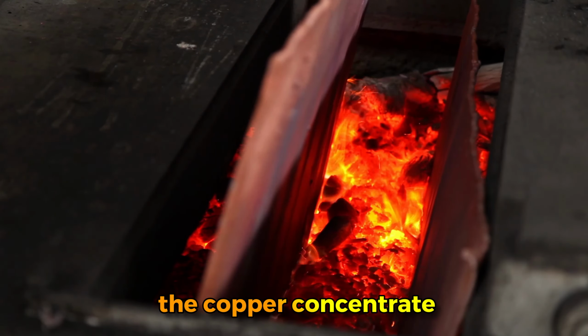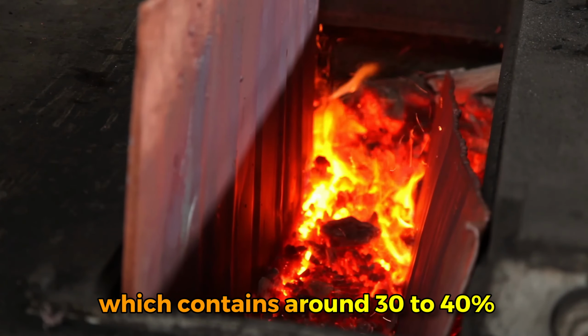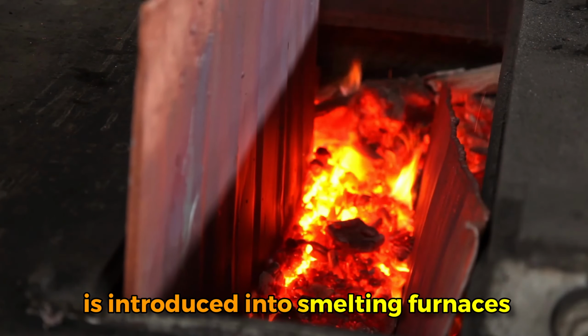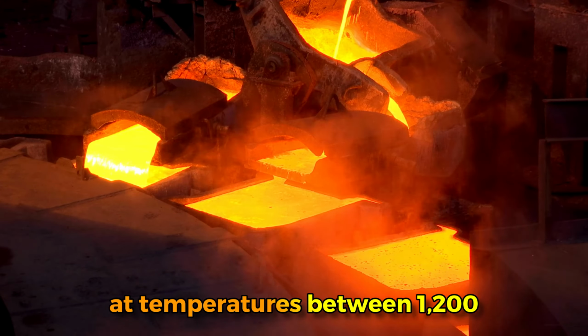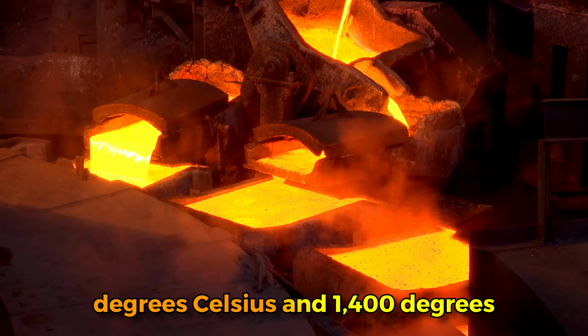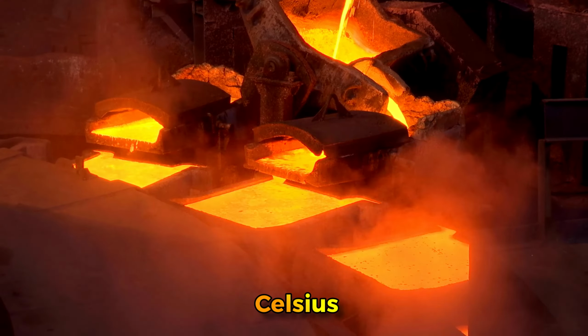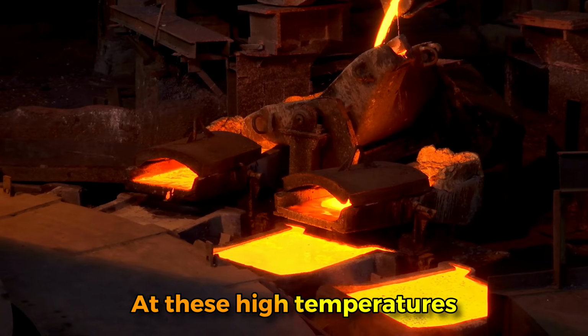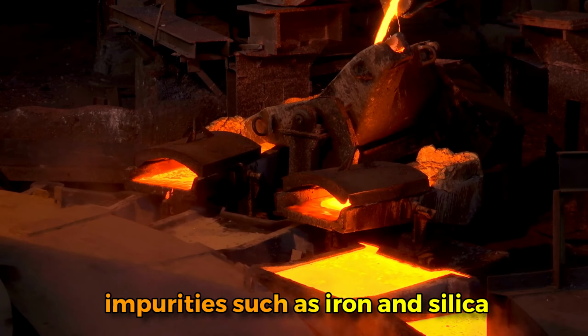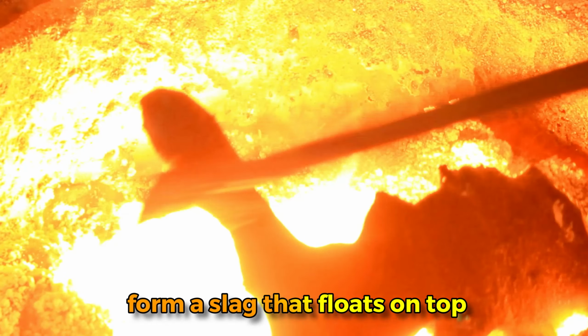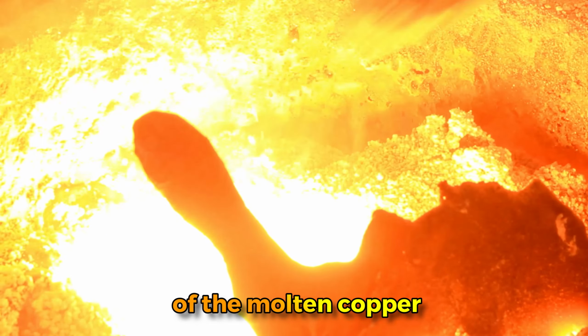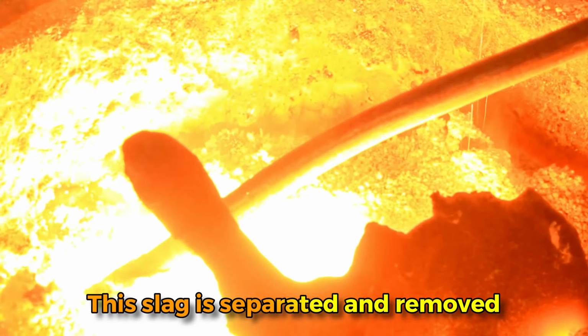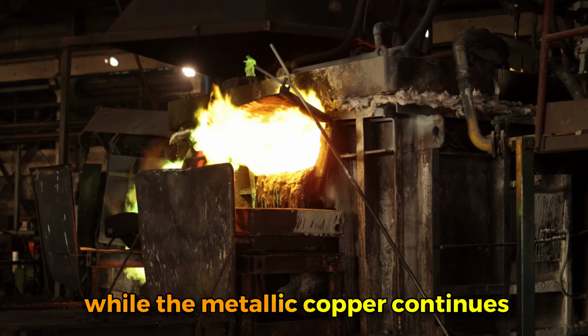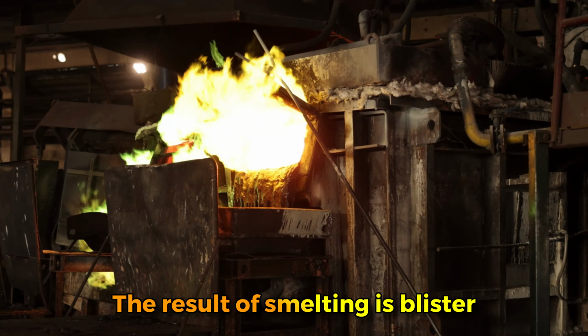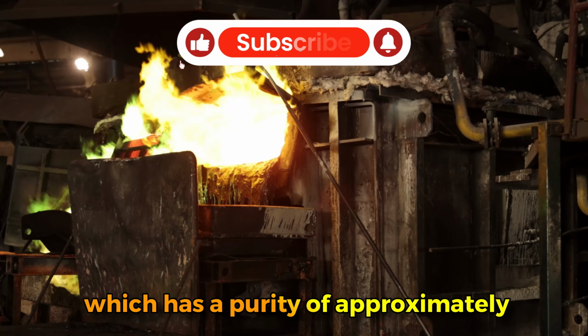In this process, the copper concentrate, which contains around 30 to 40% copper, is introduced into smelting furnaces at temperatures between 1,200 degrees Celsius and 1,400 degrees Celsius. At these high temperatures, the ore melts, and non-metallic impurities such as iron and silica form a slag that floats on top of the molten copper. This slag is separated and removed, while the metallic copper continues to be processed. The result of smelting is blister copper, which has a purity of approximately 98%.